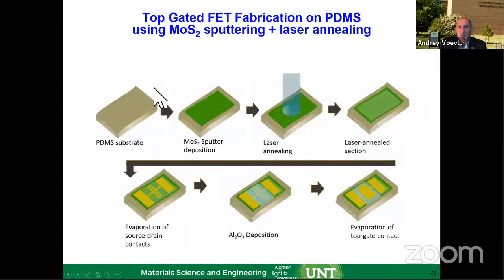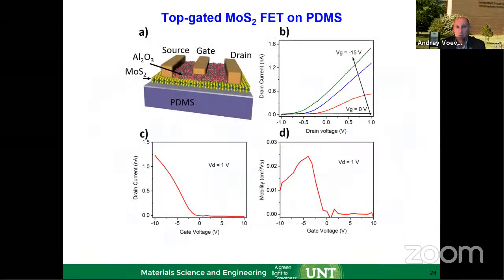And then the process became like this. We're taking the PDMS substrate, sputtering molybdenum disulfide, and laser annealing it, so we can have a semiconducting channel. Now we have a semiconducting channel right over here. Next step is to deposit, with e-beam lithography and evaporation, the source and drain contacts. Then we put a gate that can be boron nitride, in this case aluminum oxide made by ALD. And now we can have a top gate, and here we have a device directly fabricated on PDMS structures without any lift-off techniques.